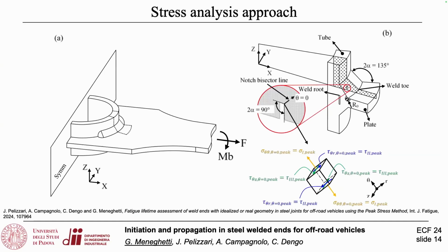The stress analysis, according to the peak stress method, has to take into account the peak stresses at the weld toe or weld root. Anyway, here we are. So we took the linear elastic peak stresses at the weld toe, plate side, tube side, and also at the 2 points of the weld root, since it is a slot, as we have noted before. So you see here the mode 1 yellow, mode 2 blue, and mode 3 linear elastic peak stresses, which must be input in the design equivalent peak stress we have seen before.